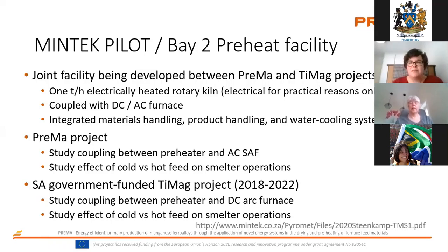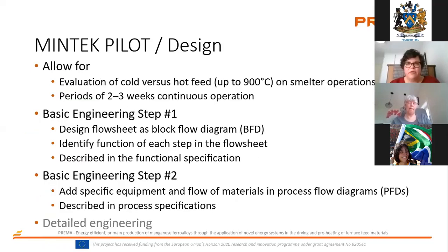So what we want to do is understand that coupling much better, both for the PreMa project and the TiMag project. For PreMa, it's a 3-week campaign. We will study the effect of cold feed versus hot feed on smelter operations, and we will focus on electrical energy consumption in the smelter as well as CO2 production, because those are the two primary criteria of the PreMa project. The TiMag project is managed by my colleague Eli Ringdalen, whom many of you are familiar with. As I said, it will study the coupling between the preheater and the DC arc furnace, specifically for titaniferous magnetite smelting. He plans more than one campaign to study the effect of cold versus hot feed on the DC furnace operation.